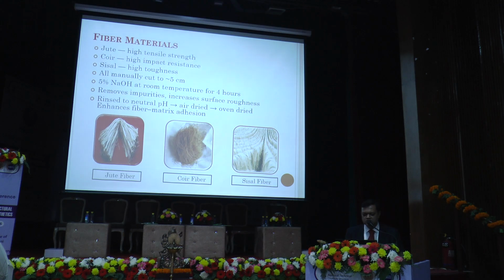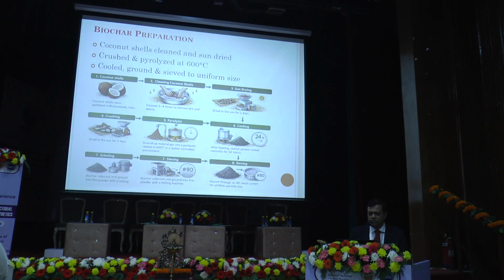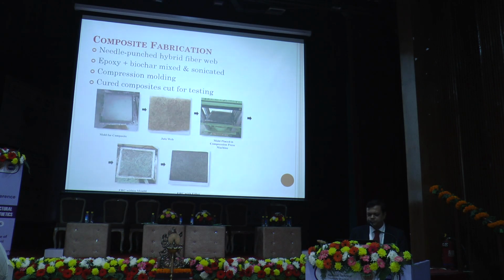So these are about the raw materials that we have been using. Jute, coir and sisal are treated with 5% sodium hydroxide at room temperature to remove the lignin, then rinsed with water to get a neutral pH, then air dried, oven dried, and used for composite manufacturing. This is the process for biochar preparation: pyrolyzed at 600 degrees Celsius, coconut shells were ground and sieved to get the coconut shell biochar.